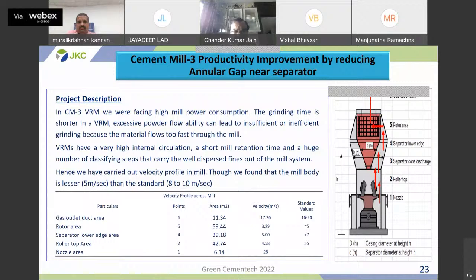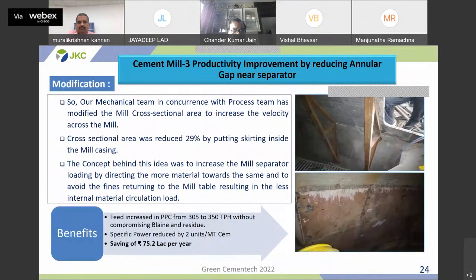The next project is the Cement Mill 3 productivity improvement by reducing annular gap near separator. In Cement Mill 3 VRM, we were facing a high power consumption issue, and we were not able to get the desired TPH. So cross-sectional area was reduced by putting skirting inside the mill casing near separator.